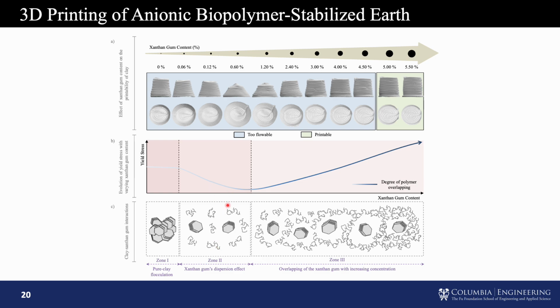So at a very small concentration, it will disperse the clay particles. So you see the buildability here, and it will gradually decrease. Now you see the yield stress here, the yield stress gradually decreases too, right? But at some point, if you keep increasing the polymer concentration, the polymers start to overlap with each other, right? And then if you keep increasing the polymer concentration, they overlap again. Then it will create this kind of three-dimensional polymer network, which will gradually increase the yield stress, increase the storage modulus, increase the viscosity. Then if you print this material, your buildability starts to increase again. Gradually, if you keep increasing, at the end you have this kind of material, which is pretty nicely printable.